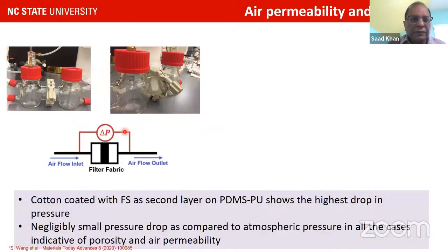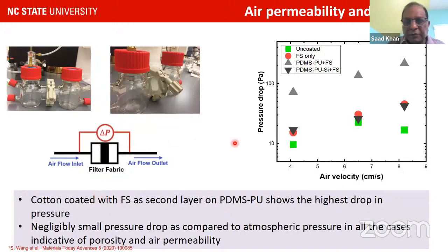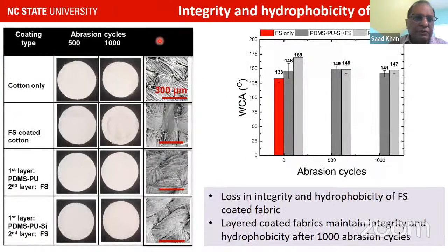So we did some airflow measurements using a very crude approach that we have developed in our lab for doing some other things. What we found was that the pressure drop does go up when we coat it, but it's not too bad considering the atmospheric pressure. So we do have pressure drop changes and an increase, but it is not as bad as you would fear. So it is something that's viable and doable. But the most interesting thing is the abrasion resistance.